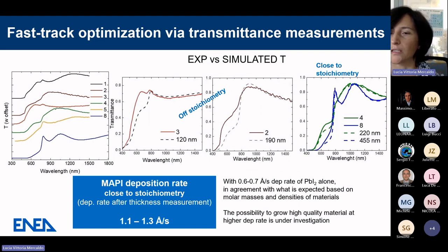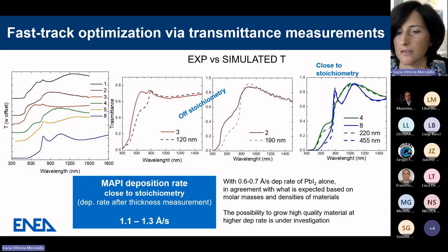And here I'm showing a slide where we can see how the transmittance measurements can be helpful while controlling the stoichiometry of the materials under preparation. So here there are examples of transmittance spectra measured for different samples prepared with different deposition conditions, like the source temperature or the quantity of precursors in the crucibles.